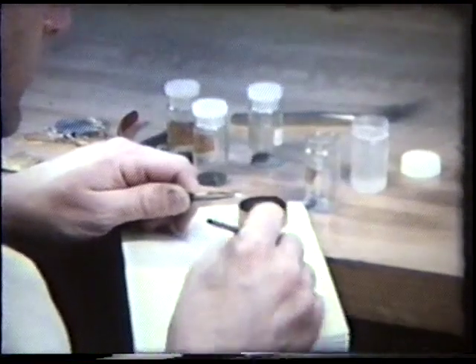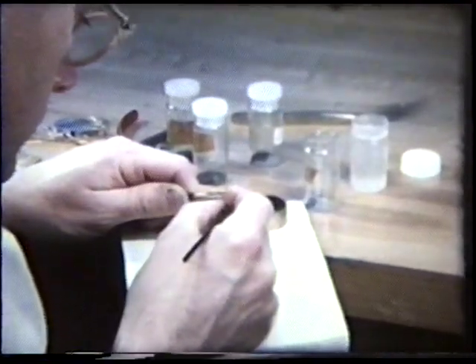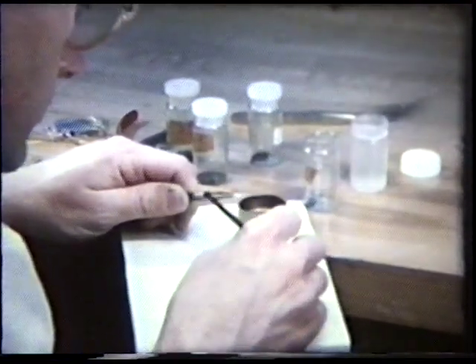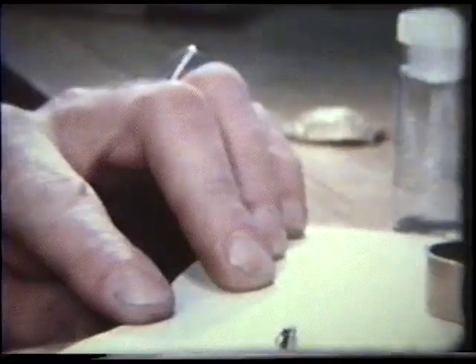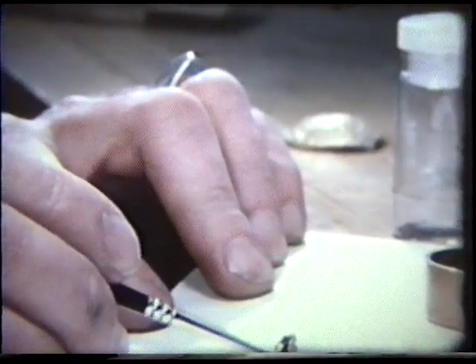Surface enrichment for this piece is applied in the form of minute balls of gold. These are made by cutting a thin sheet of gold into fine chips, mixed with powdered charcoal, and placed in an iron box. These chips form perfectly round spheres of gold when heated to 2000 degrees in a kiln. They are then separated from the charcoal and sorted according to size with sieves.